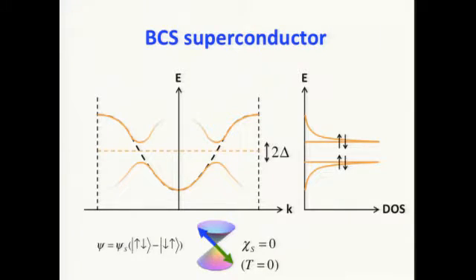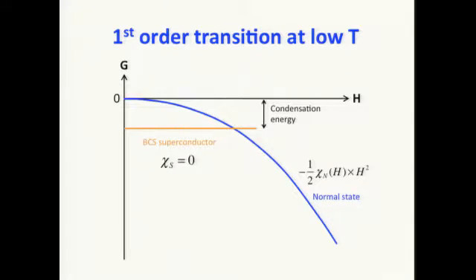The Cooper pair wave function in the BCS superconductor is characterized by spin singlet pairing with a spatially even wave function. In the zero temperature limit, when all the quasi-particles are frozen, the spin susceptibility of a spin singlet Cooper pair is 0. That just means the Cooper pairs are not responsive to an external magnetic field. That actually gives rise to a first order transition in the magnetic field induced superconducting to normal metal transition.